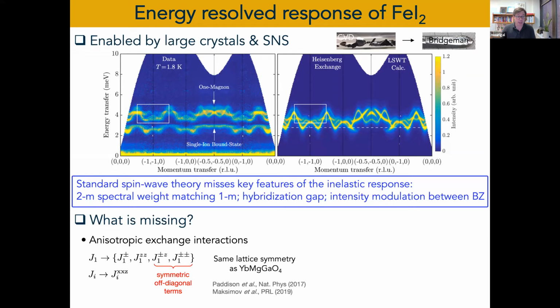So what we had to do in order to explain the details of this data is extend our exchange interactions from being Heisenberg to having all the symmetry allowed terms on each nearest neighbor bond. Okay, so for the triangular lattice, the exchange interaction is actually a matrix, and that matrix has 4 terms that are independent.